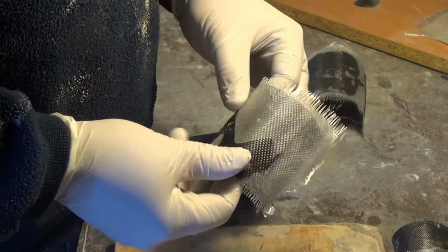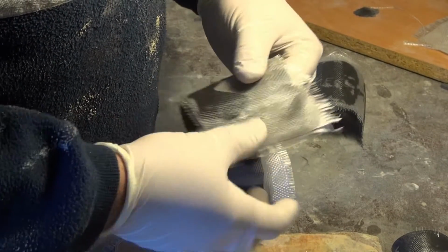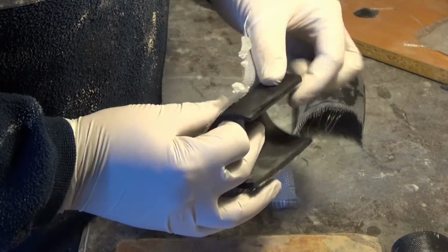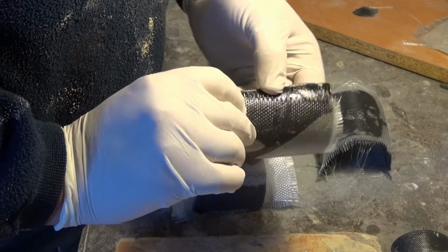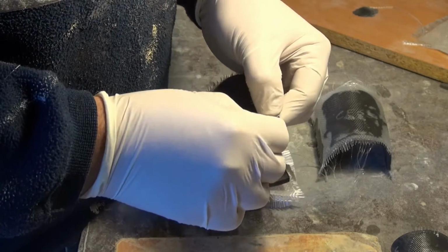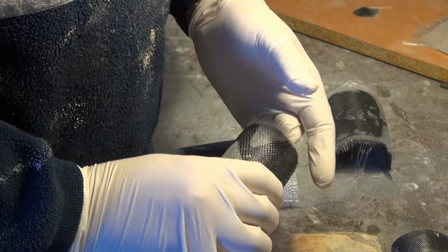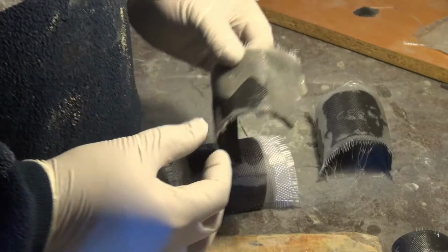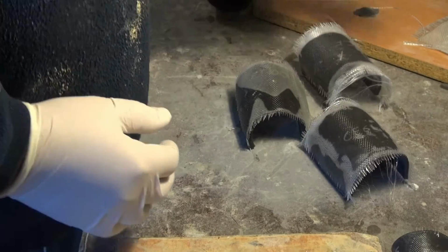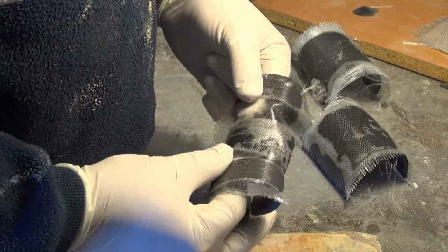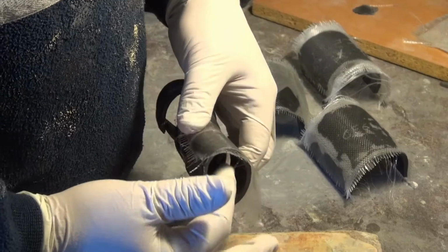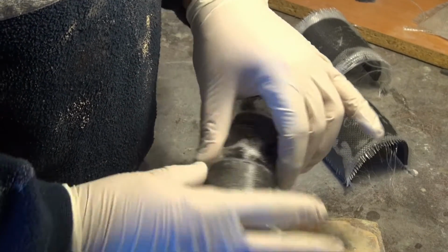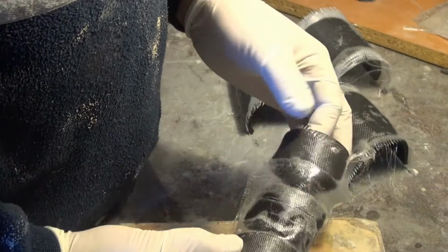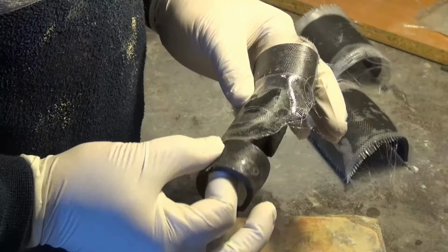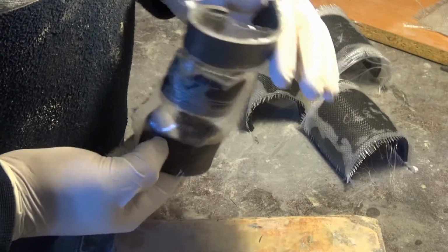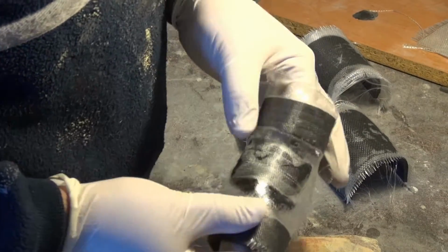On the CF100 sample, the fiberglass has not properly adhered to most of the piece, but once again, applying a layer of resin and allowing it to cure before applying the fiberglass can solve the problem. On the smaller pieces, to which the lighter fabric was applied, the adhesion was good on the craft foam and CF65 samples, but on the CF100 sample it was not as good, probably because of the shape of the piece and the fact that the fabric was stretched to cover the three pieces simultaneously.